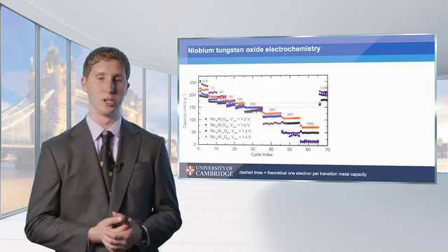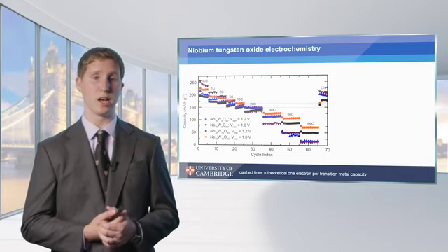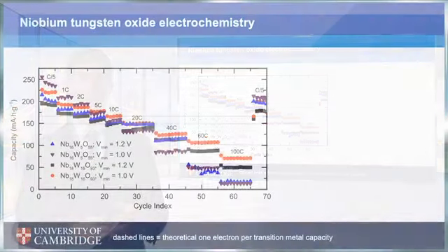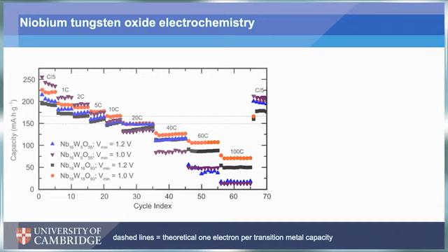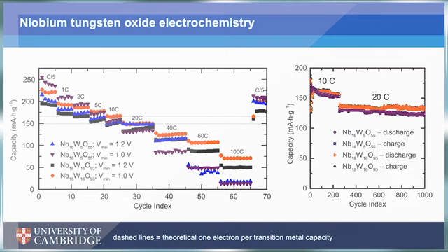Now, if we look at that data in summary here, these little dotted lines are showing us where the theoretical 1 electron reduction capacity corresponds to. So it's around 150 to 170 milliamp hours per gram for the two different materials. And what we see, though, is at 10C, so 6-minute charge or discharge, we're accessing the full 1 electron theoretical capacity. And then anything slower than that, we're actually doing multi-electron redox chemistry.